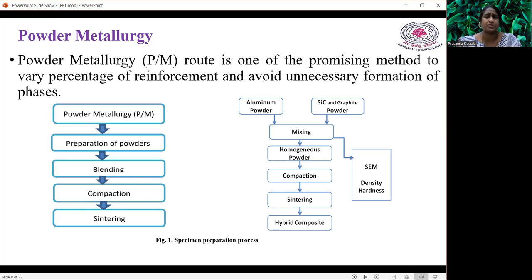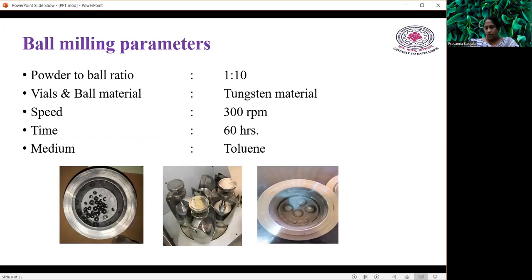So powder metallurgy makes sure that whatever powders we blend, compact and sinter, it gives uniformity of bonding and uniformity of the structure is attained. For the ball milling operations, the ball milling parameters are a powder to ball ratio of 1:10. The vials and balls are taken as tungsten material, and the speed is taken as 300 RPM for a duration of 60 hours. It is being soaked, and the medium used is toluene.